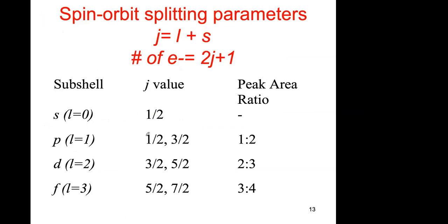We also mentioned the different orbitals and the spin-orbit splitting parameters, J. For example, you will see only one peak for an S orbital, but for a P you will see two, and for a D you will see two, and for F you will see two. That is if the electron analyzer has enough resolution to see both of them. If the energies are pretty close, maybe you will see one. But this is pretty easy to identify, whether it's an S, P, D, or F orbital.